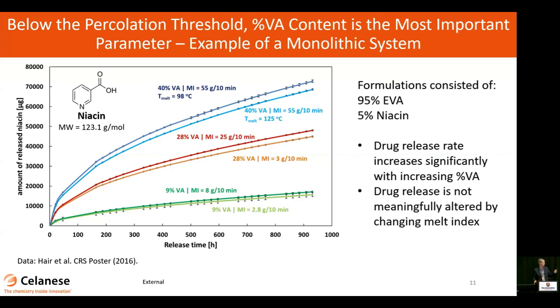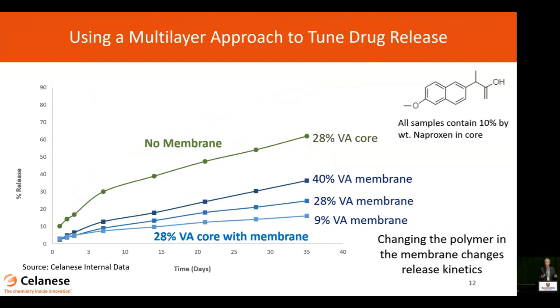The other thing that you can see, if you look closely and compare the 2 red curves, is that we actually did 2 different copolymers in this. We used a 3 melt index and a 25 melt index copolymer of 28%. You see there's essentially no meaningful difference in the release characteristics of those two. And likewise, if you compare the two different molecular weight, or melt index, versions of the 9% copolymer, again you see a very similar release characteristic. So that was a monolithic system where you just force the drug to dissolve and diffuse through the polymer matrix and you characterize its release.